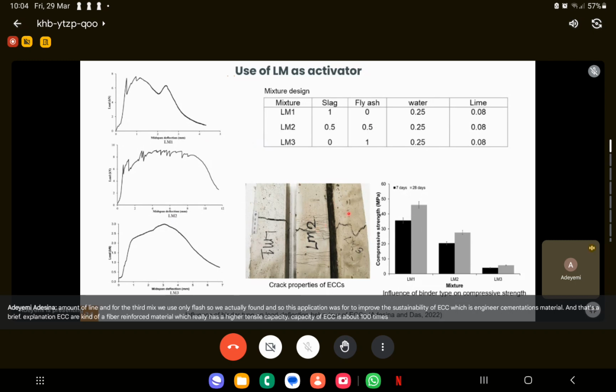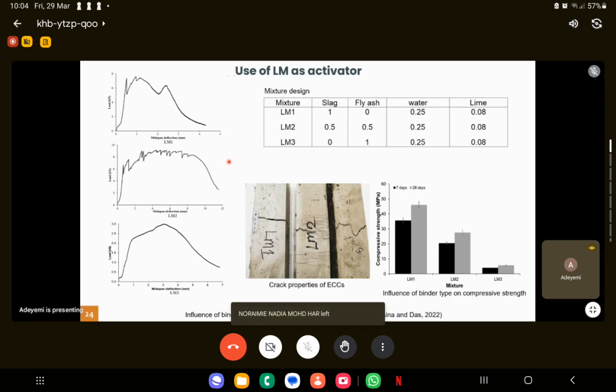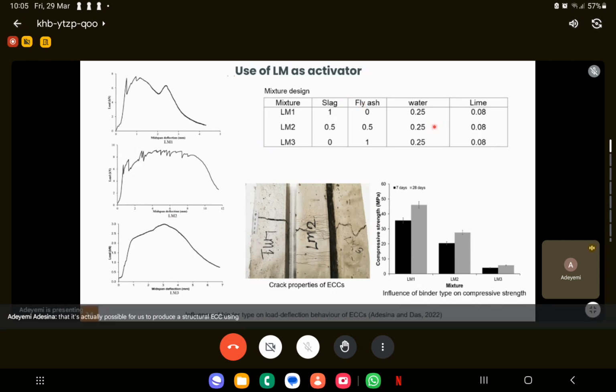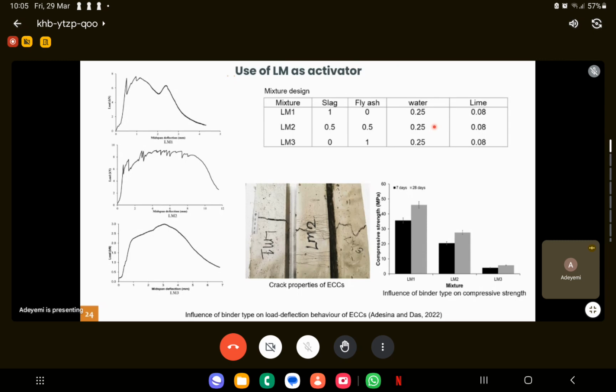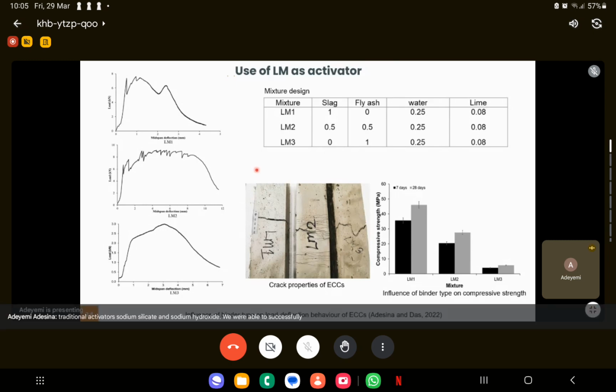So from the results, we're able to see that it's actually possible for us to produce a structural ECC using just waste products, in this case slag and fly ash, in addition to lime. So instead of producing concrete with cement or using the traditional activators, sodium silicate and sodium hydroxide, we were able to successfully produce structural grade cementitious material with the use of lime as the activator.